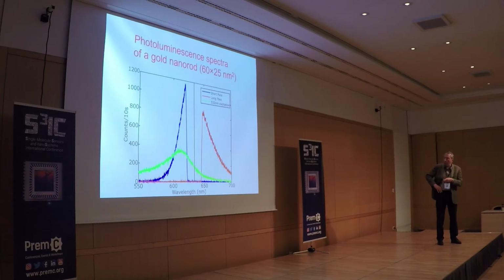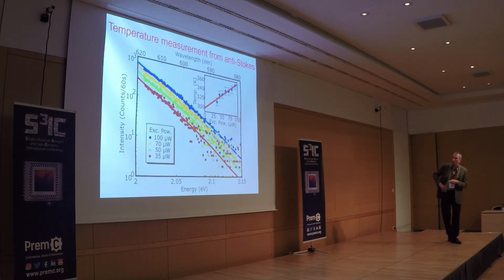Right, let's move to the next one. Yeah, so this is just a demonstration that this really works. You can measure the temperature while you are heating, but by extrapolating to zero heating power. Of course, you need some power to measure, because without power, there is no photoluminescence. So you need to extrapolate to really low powers, and by extrapolating, you get room temperature. So you can easily measure absolute temperature, even though you are not heating too much with the particle. You need a bit of light, of course, to see the anti-Stokes photoluminescence.